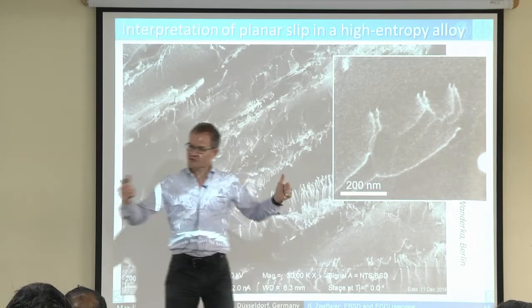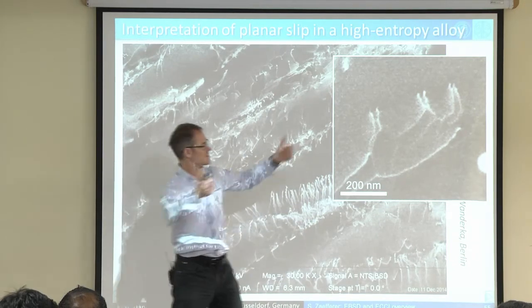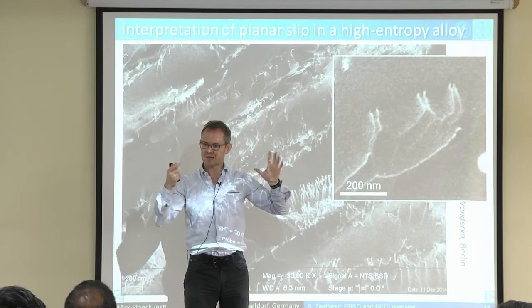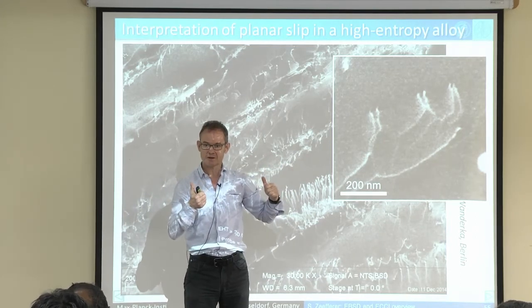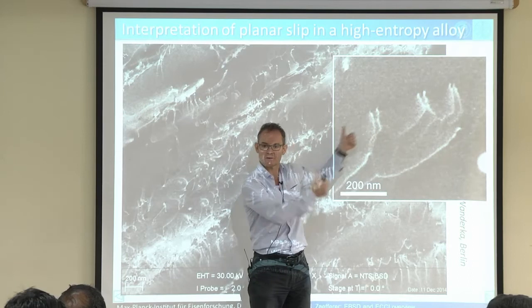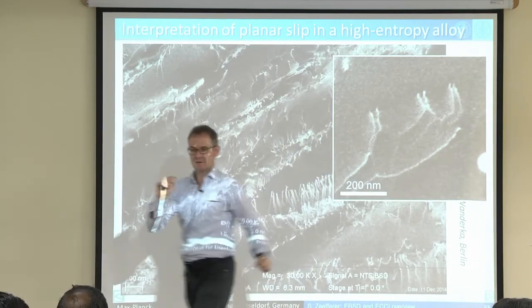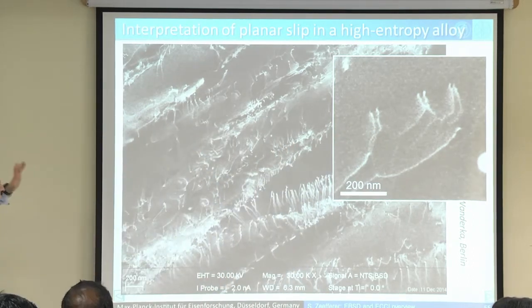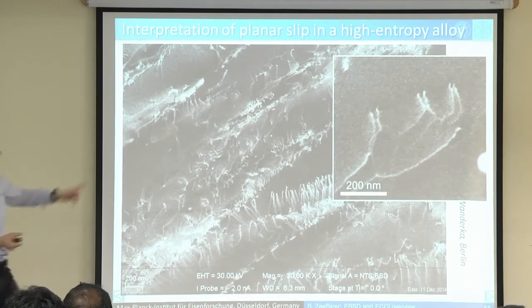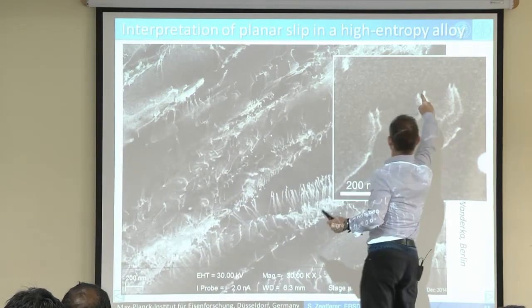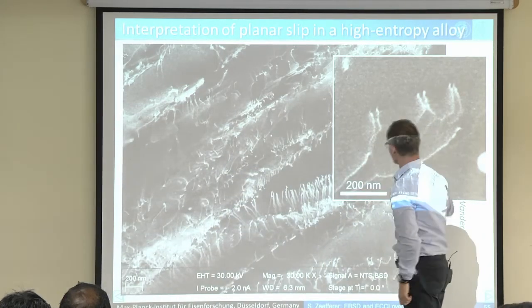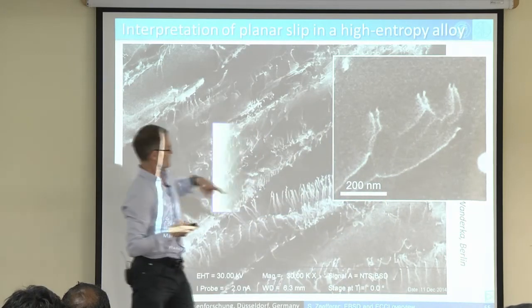But it could also be that these dislocations are of the same character, and they are just grouping together because they are destroying a short-range order. So one dislocation is destroying it, and the other one is repairing it again. So that could be the case as well. Actually, in TEM, it's very difficult to distinguish between a plus and a minus dislocation. But here in ECCI, we have quite an easy tool because we are seeing the details of this dislocation oscillation, and we can calculate from that the Burgers vector. And, oh yeah, I'm coming to this in the next slide.